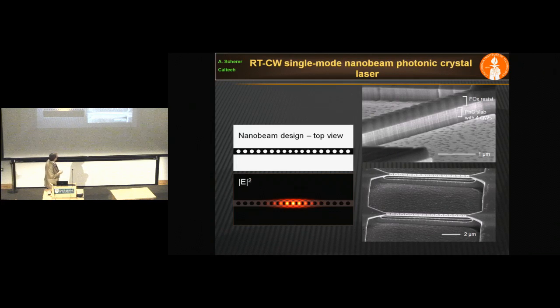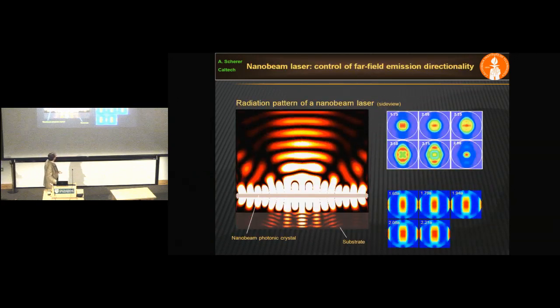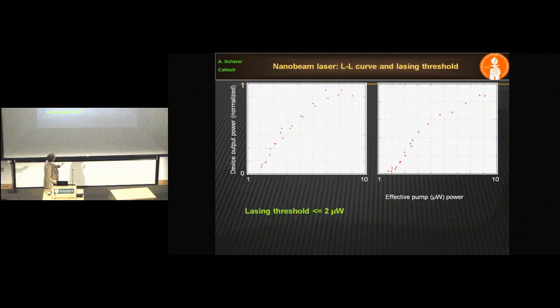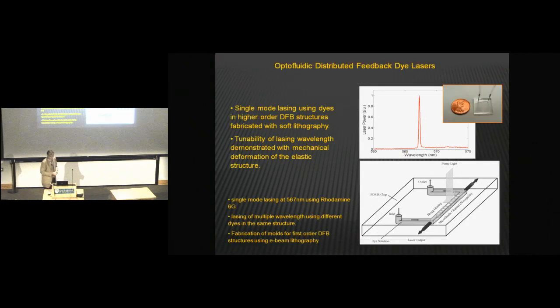These are indium gallium arsenide photonic crystal wires, and they basically lase. And you can actually get CW, room temperature lasing out of these structures. This is what the mode really looks like, and you see that the thresholds are pretty nice. They're on the order of 1 or 2 microwatts. So very low power you have to put in, and you get the material in, you get a signature of the material around it. Now I can make a laser differently.